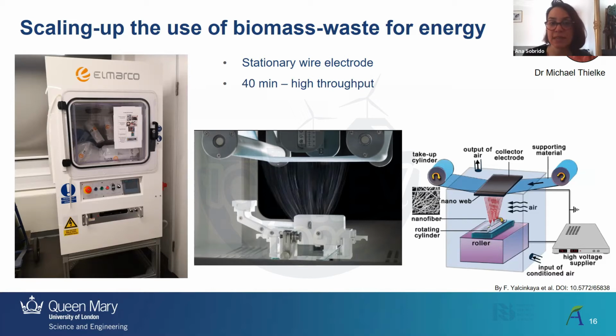And in 40 minutes, we can get up to 35 centimeters area, which is really good, and then we could play with the thickness as well, and with different aspects. So this is going to be the next step once we have our materials. The idea is that we can make these biomass lignin-derived fiber electrodes competitive with the current commercial materials that are used for the different applications.